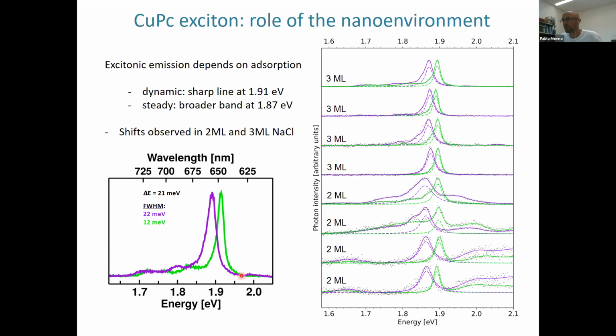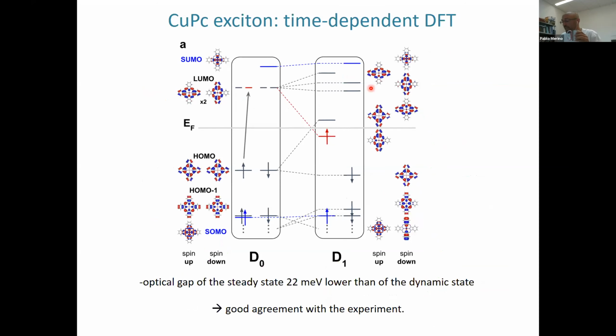And we did time-dependent DFT to calculate the excitons. And well, it's curious that in this case, that is an open shell molecule, the SOMO and the SUMO are not the frontier orbitals; they are below the HOMO and the LUMO. So then the lowest energy transition, the lowest energy electron hole excitation is a HOMO-LUMO, and this may explain why, okay, I'm almost done, this is basically why the emission from zinc, which is a closed shell, and copper is so close.